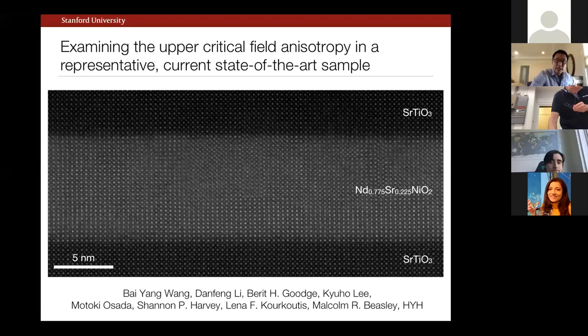But I wanted to end with some fairly recent things that we've been working on, thinking about the upper critical field anisotropy, a little bit trying to now delve into the physics of the superconductivity of the system. I should first thank that this benefited a lot from the expertise and insights of Mac Beasley. And in some sense, this is a picture of one of the samples that I'm going to show you. The idea is that we've been working harder and harder to try to clean up the materials. So I think this is both representative, but also kind of state of the art. And for some reason, a little bit unknown to me, at least within what we've measured, this composition seems to have the nicest crystallinity. You can see here that it's fairly coherent, but it does still have extended defects, right? So this is kind of where we're at materials-wise.